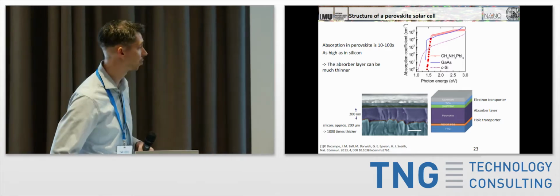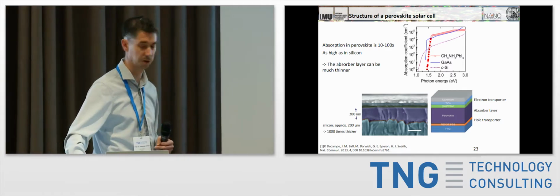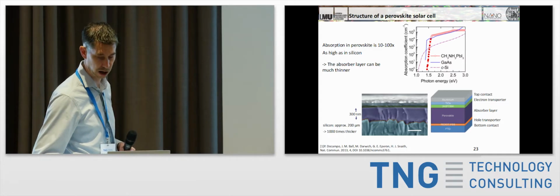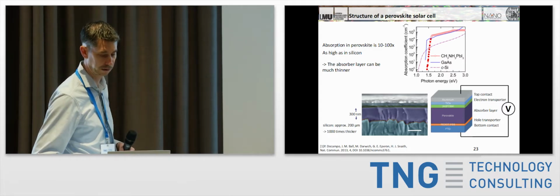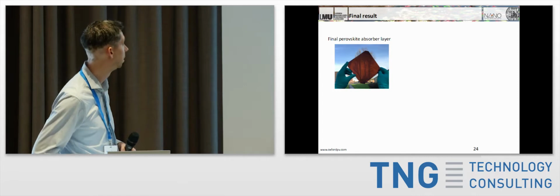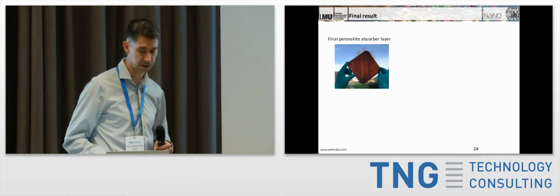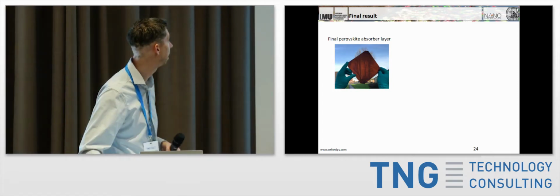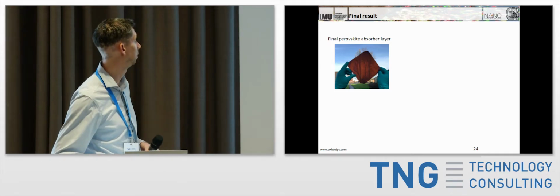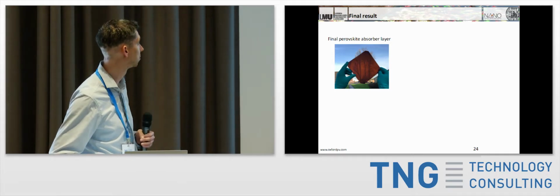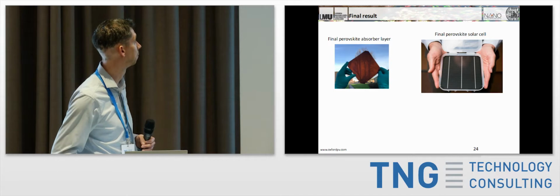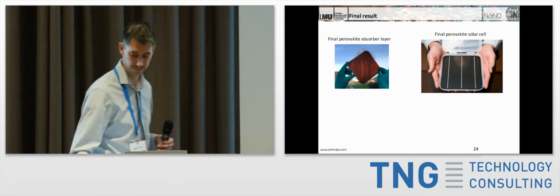They basically make sure that the electrons go in one direction and the holes go in the other direction. We have top and bottom contacts, and that then creates our current and our voltage in there. All right. So that's what a final perovskite absorber layer looks like, made out of methylammonium lead iodide. You can see it's a very deep brown, so it's absorbing most of the light that comes through the visible spectrum, and that's what the final perovskite solar cell looks like.